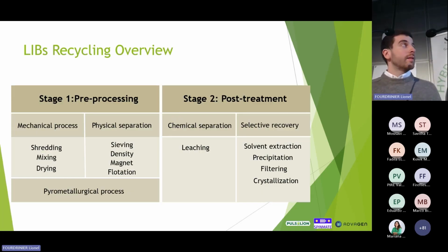So now regarding the recycling technologies, when you read about battery recycling, you might have seen that people talk about 3 different possibilities for the recycling of lithium-ion batteries: the hydrometallurgical process, pyrometallurgical process, and direct recycling. But when we talk about recycling at industrial scale, we have to distinguish between the pre-processing and the post-treatment. So in the pre-processing, you can find basically mechanical processes, physical separations, and pyrometallurgical processes. And then the post-treatment is based on a hydrometallurgical process where you have a chemical separation and selective recovery.